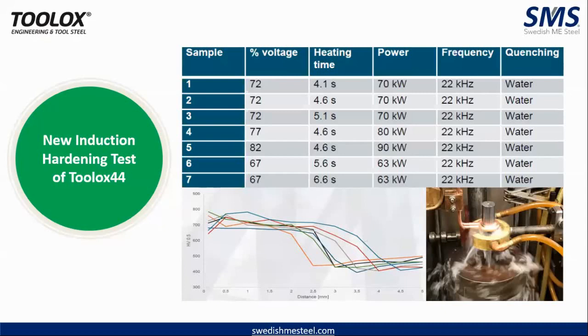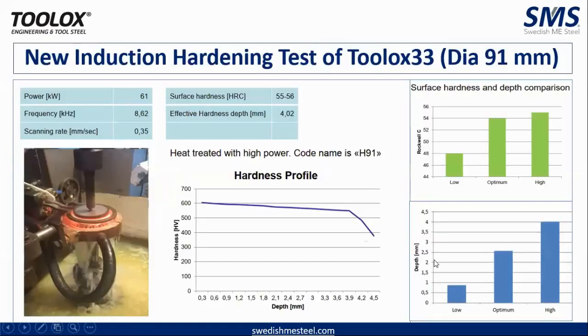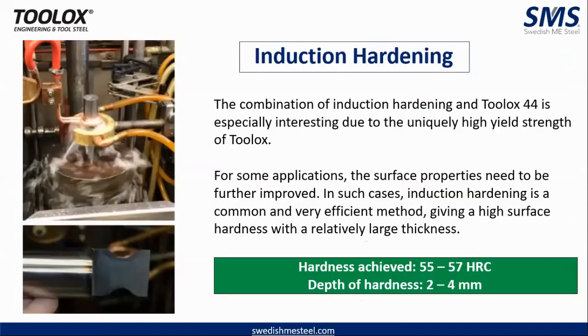So we have done many tests with Toolox 44 in induction hardening. This is one such test, which shows the various graphs involved. So this is another induction hardening test which has been done. This is for Tulox 33, 30 HRC material. The quenching medium is water here. So obviously it has been hardened with the standard procedures being used. There are various ways in which you can play with this, but the point to note is that you can achieve 55 to 57 HRC with a depth of hardness of 2 to 4 mm.